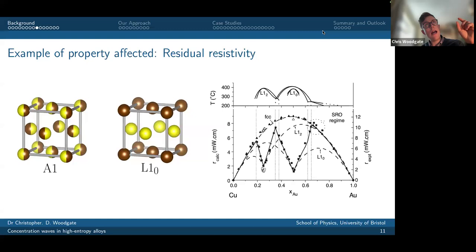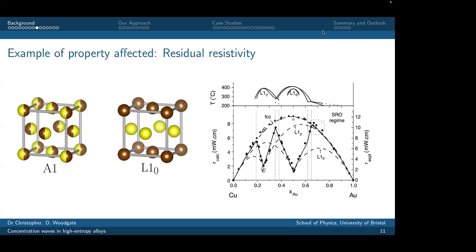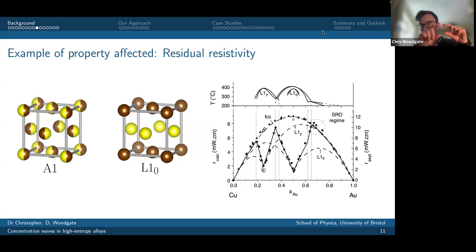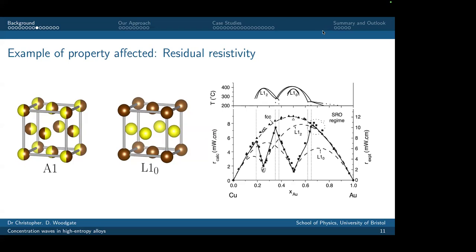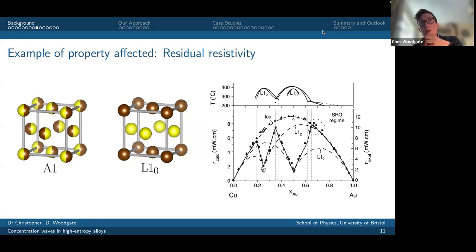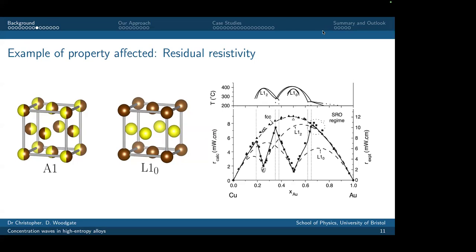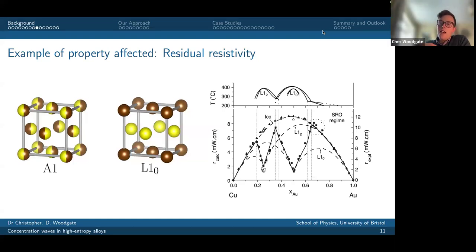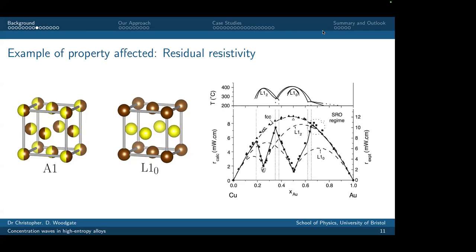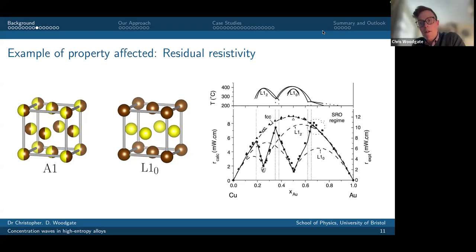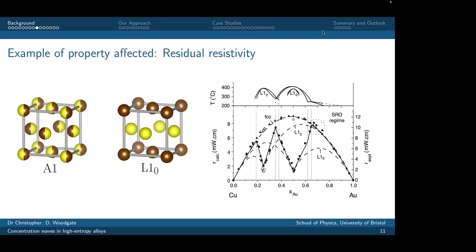For the most part, when I'm talking about disorder, what I'm thinking about is the substitutional disorder on lattice sites and how that introduces this smearing in the electronic structure of the disordered solid solution. In principle, you can include vibrational disorder and so on, if needed. In this approach, you've got vibrational entropy terms, for example, and how they alter the transition temperatures. But generally, what I'm thinking about is having a configurational entropy describing the electronic structure of the disordered solid solution, and then seeing how my free energy changes as I apply atomic scale chemical fluctuations. Good. Okay.